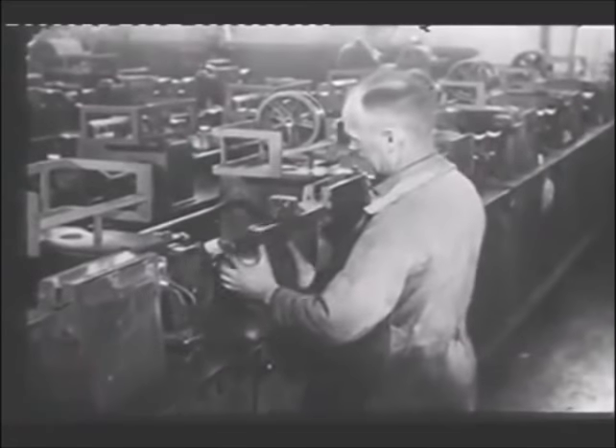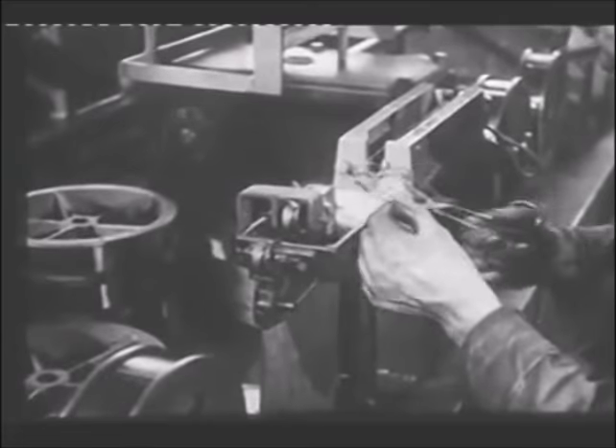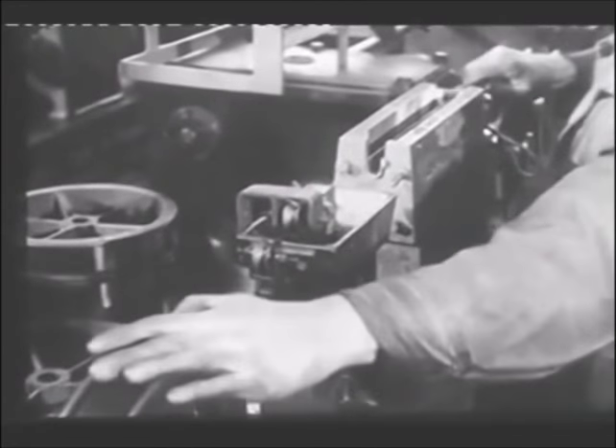From this stage, diamond dies are used, until after some 200 or 300 drawings, the original bar has been transformed into as much as 200 miles of fine wire, of diameters down to 6 microns, or 3/10,000ths of an inch.